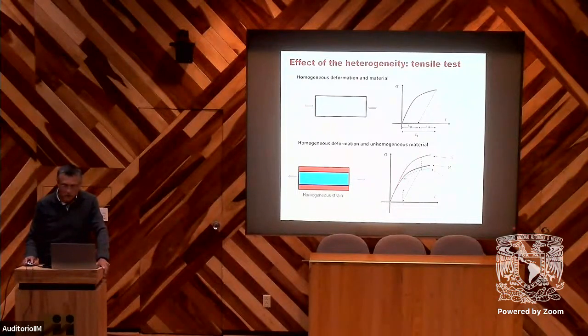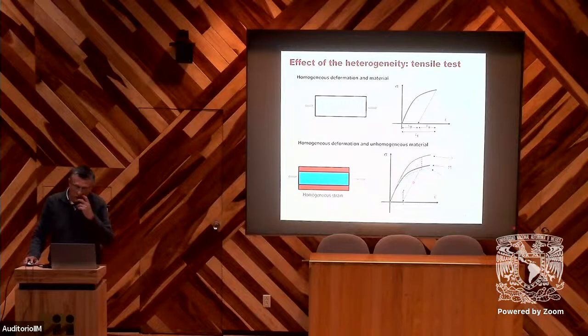The macro behavior is an average of the two behaviors. And we can see the differences of the level of the stresses when we apply a load. And if we unload, in macro behavior we have 0, but we can see here that we have tensile residual stresses near the surface, and this will be equilibrated by compression inside the material. In this case, it's simple to make calculations because we consider here that we have homogeneous strain. That means we have the same strain in all the material.